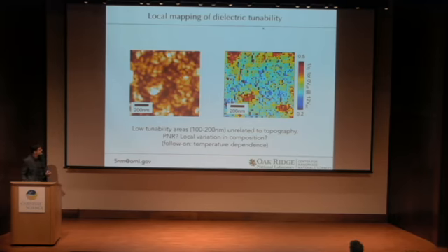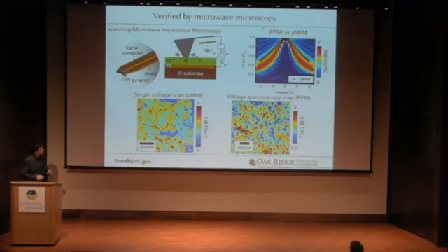Another thing I wanted to mention is that we were able to verify this approach by doing a direct comparison between this PFM-style tunability measurement and microwave measurements, where microwave microscopy directly probes the capacitance under the tip. The inverse tunability comes out very close between the microwave, which is the red signal, and the PFM derived. So this approach really works.